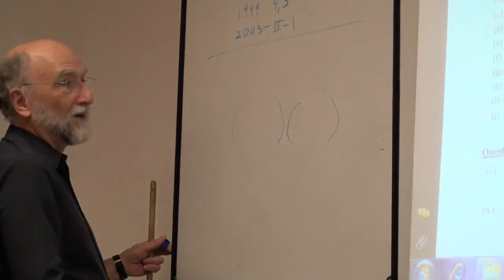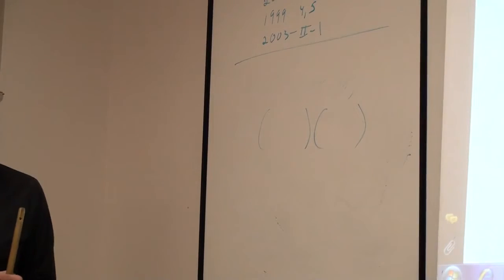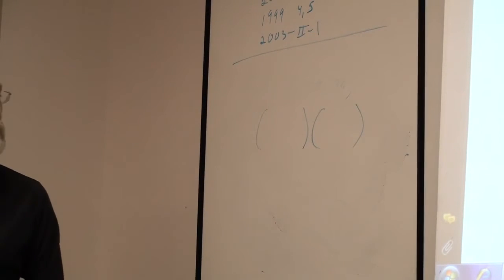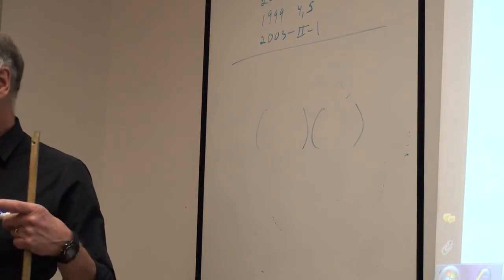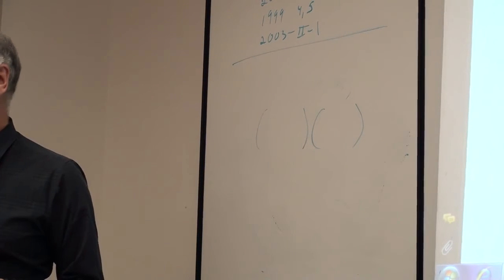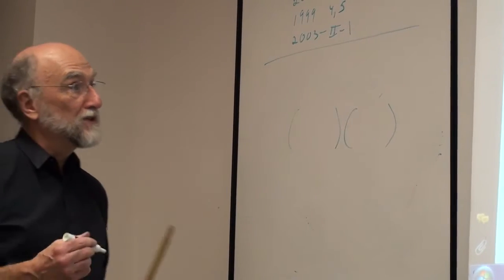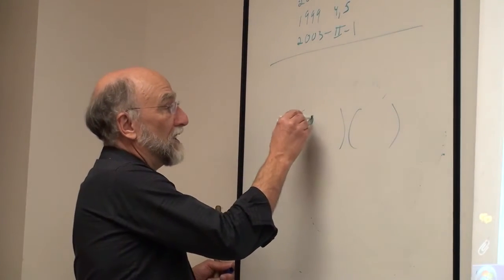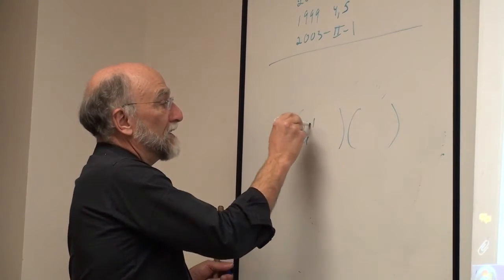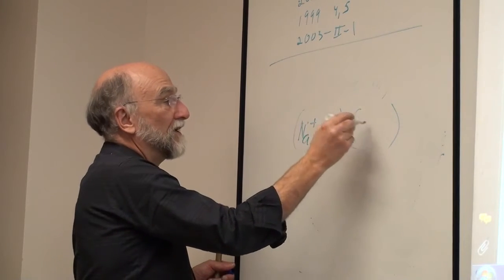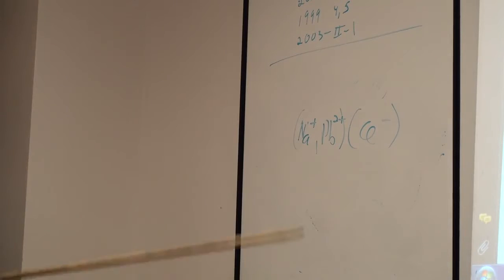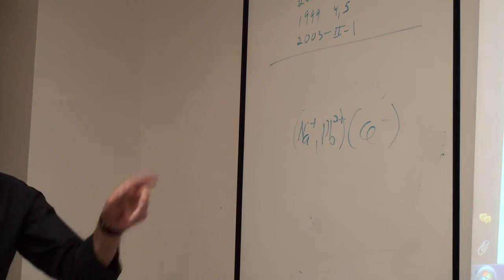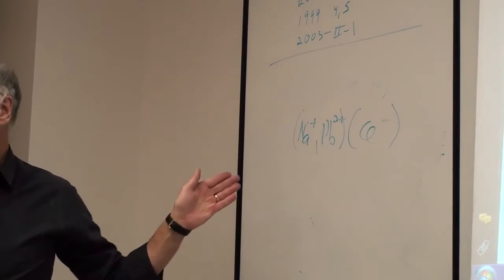And the liquid, what you've got. In PbCl2, you have very few complexes. Lead is so big that it doesn't form complex ions, as I said last week. So, to all intents and purposes, you would have sodium ions and lead ions on the cation sites and chlorine on the anion sites, but the ratio of the number of cation to anion sites clearly changes as you change the composition.